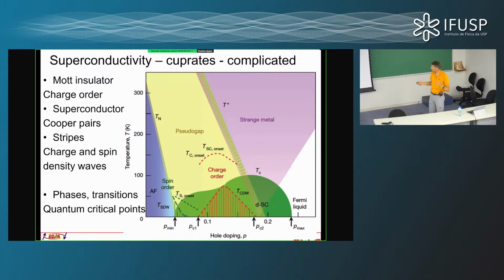This happens in reality, and perhaps the most famous example is the family of materials called cuprates, which contain exactly such square lattices of copper and oxygen. And it turns out that indeed, if you have exactly one electron per site, then you have an insulator, and in this insulator the spins order in an antiferromagnetic pattern, similar to what I had on one of the earliest slides here. Now, if you remove a couple of electrons, you make a couple of holes in this, now they can start to move around.